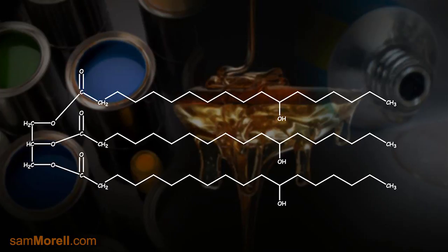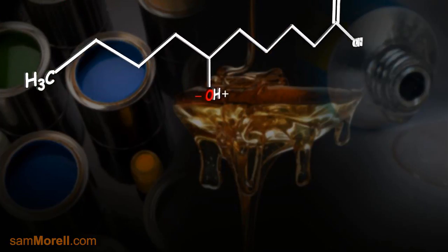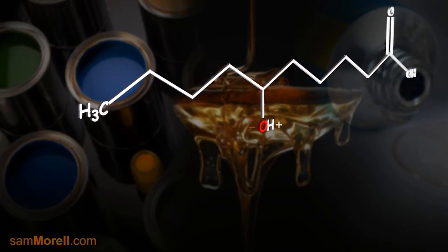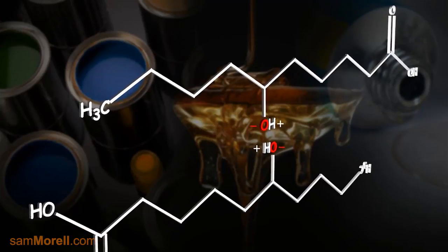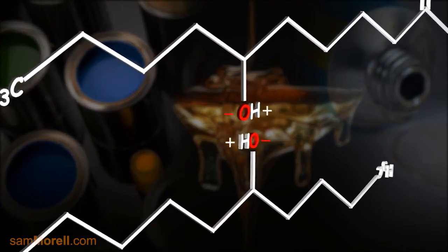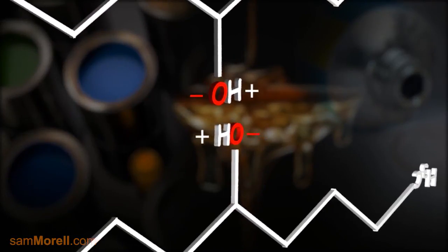Therefore, when we talk about castor oil derivatives as rheology modifiers, we're talking about hydrogenated castor oil. And it's the pendant hydroxyl groups bound to the ricinoleic acid that lead to hydrogen bonding, which in turn plays a major role in setting up a network structure. Let me show an example of hydrogen bonding between 2 carbon chains that contain hydroxyl groups. The electrostatic attraction of these molecules to each other develops a weak network which can be easily shattered with shear, yet can rebuild again when the shear is reduced or eliminated.